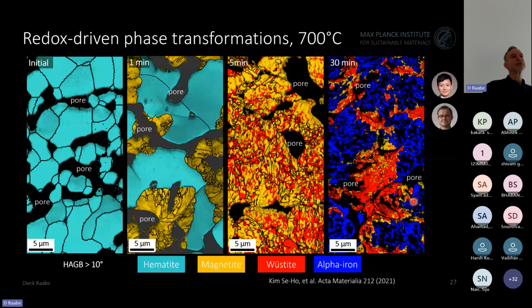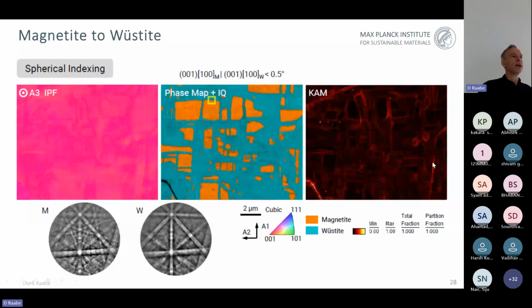And of course, you see the acquired porosity, the evolving porosity due to the massive loss of the oxygen everywhere. So you can appreciate the formation of an iron sponge, up to 45–48% of final porosity altogether. I'll come back to this. Here you see one little patch of information on which we work quite intensely at the moment.